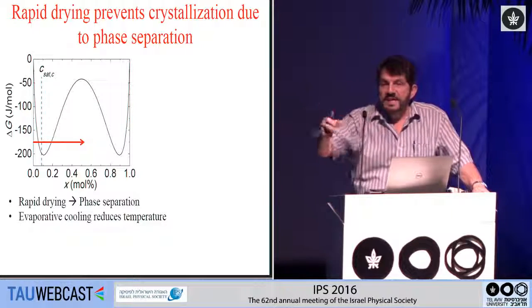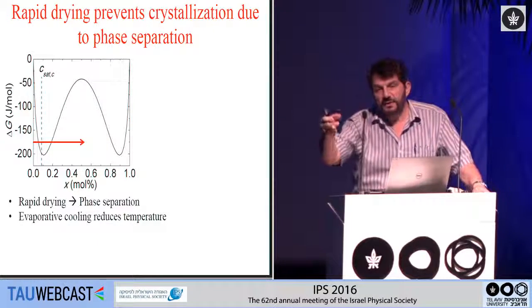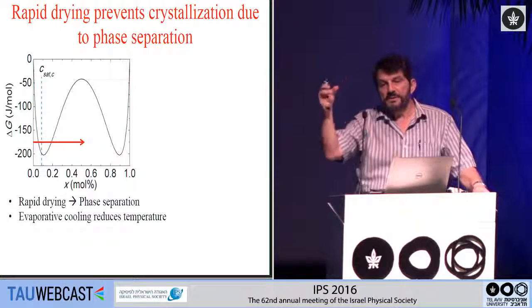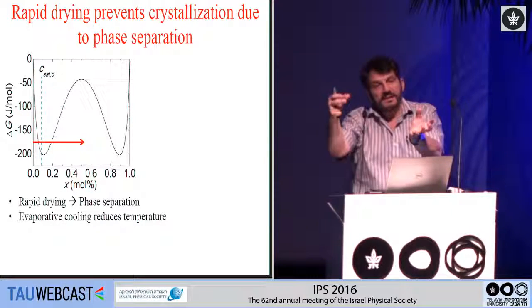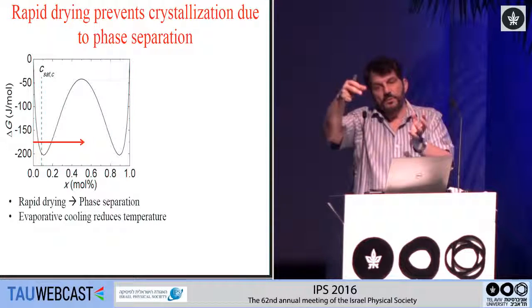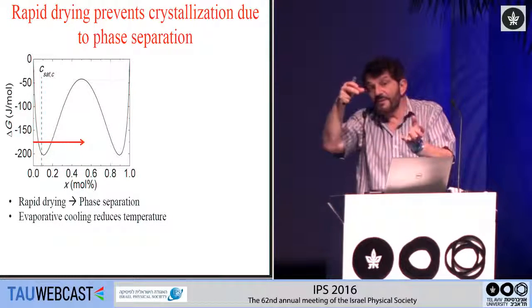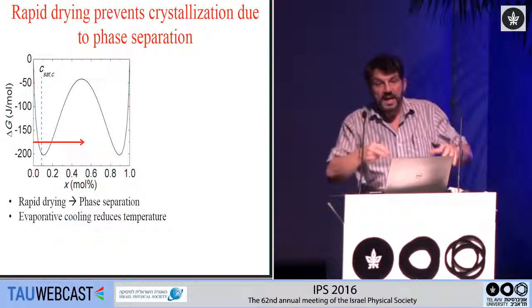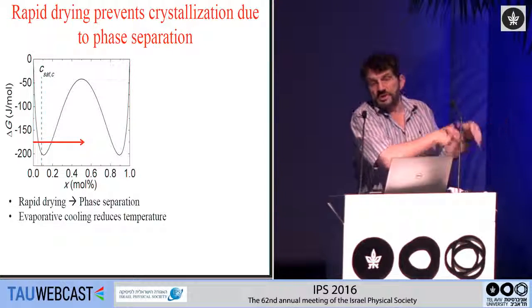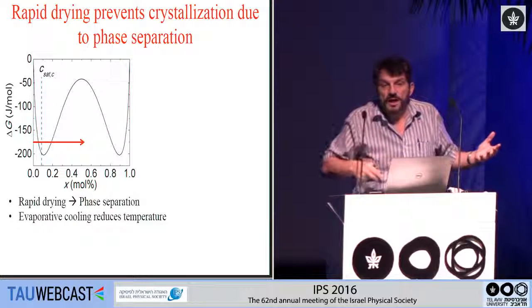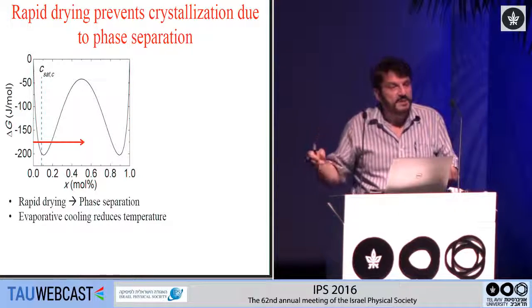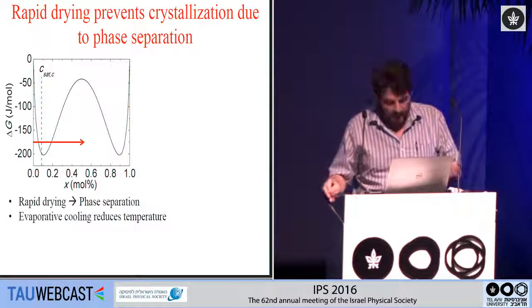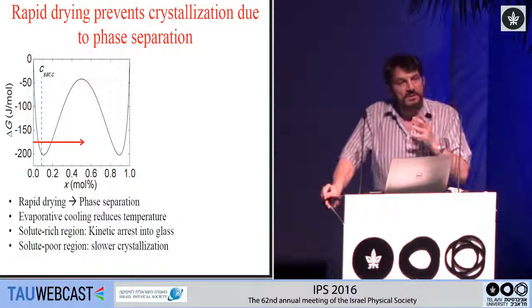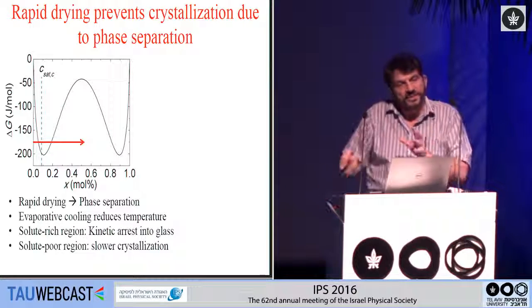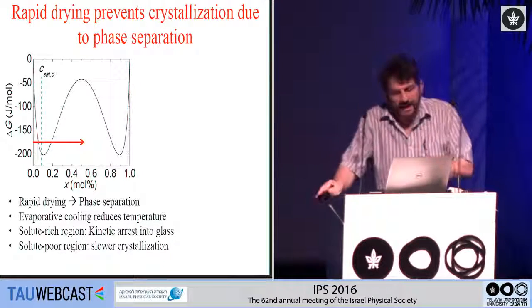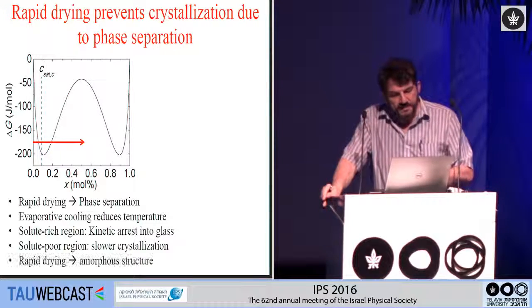It's so strongly cooled that the mobility of the atoms, of the molecules, is very low. So you're forming this supercooled network, this glass-like network. You're basically below the glass transition, and you form a connected spinodal network that's going to crystallize, but it's going to take a long time because it's so cold. In the low concentration region, the concentration is so low that it won't crystallize. So you're basically freezing out crystallization. You're kinetically eliminating crystallization due to the fact that you're undergoing this spinodal decomposition and forming this glass-like network that spans the system but doesn't crystallize.